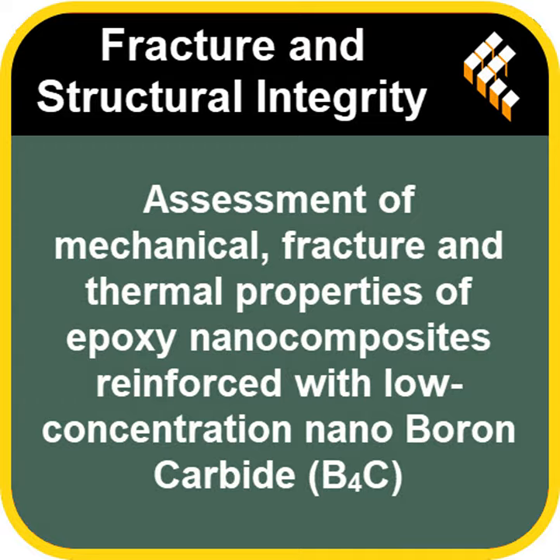And you can see evidence it worked right away when you look at the thermal properties. They used differential scanning calorimetry, DSC, to measure the glass transition temperature, or Tg. Tg is that point where the material goes from being hard and glassy to more soft and rubbery. And what they found was pretty striking. The pure epoxy had a Tg around 52, maybe 52.5 degrees Celsius. But when they added the B4C, even at just 0.4 weight percent, the Tg jumped way up to over 68 degrees Celsius. That's a really significant increase in thermal stability.